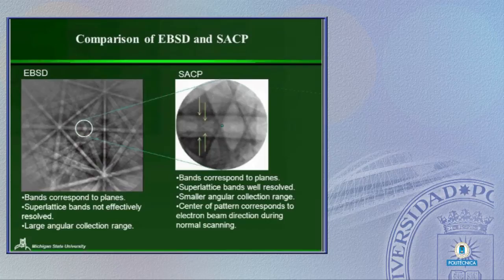So if we make a comparison of what an EBSD pattern looks like compared to a selected area channeling pattern, here's an EBSD pattern. It collects a very large angular range, probably anywhere from 45 to 60 degrees, depending on how you have the system set up. So we have these bands that now correspond to these different crystallographic planes. Where a lot of these bands come together, we get zone axes that represent high symmetry orientations. There are some limitations. Things like superlattice information are not contained in these bands. It's there, but it's really hard to see.